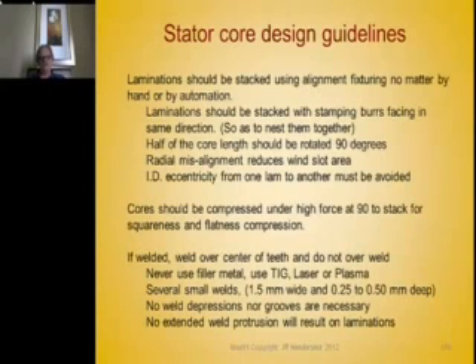When those burrs get too big, they nest together very nicely, because when a lamination is stamped, it's sheared partway through its thickness, and then it's not sheared the rest of the way. It's torn, you might say, rather than sheared. So the sheared edge is not straight. It's at right angles to the side of the lamination where it's sheared, but then it breaks away or tapers a bit where it tore, and that torn material becomes the burr. The more clearance you have between the punch and the die, the bigger the burr, and those burrs, when nested together, cause eddy current losses, shorting.